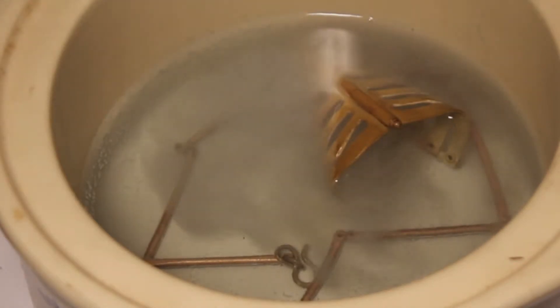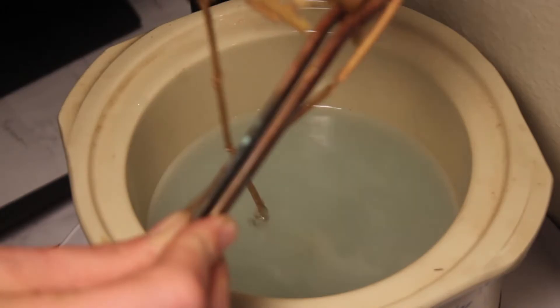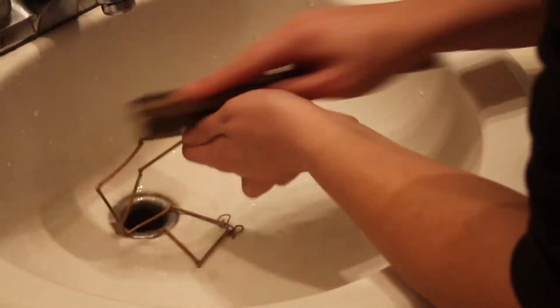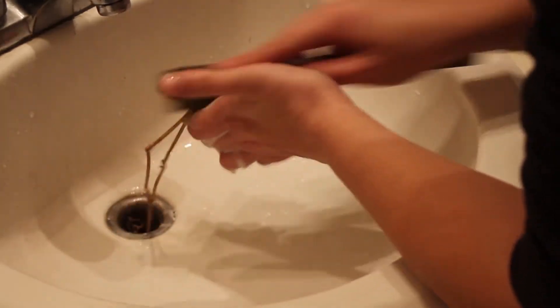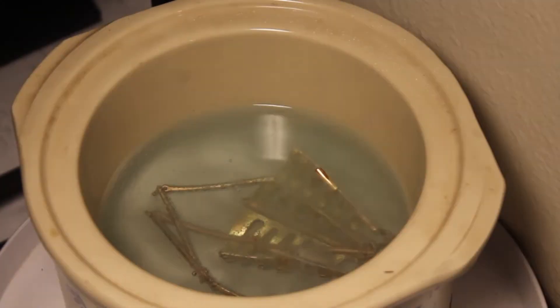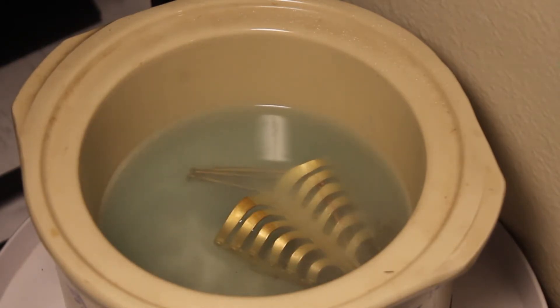It is important to flip the piece as the hydrogen peroxide pulls from the top. Once you have a coating that's taken off, brass brush and return the piece back into the pickle. You'll notice again that a chemical reaction happens. Again, flip it over because everything is happening from the top. Once you've gone through several rounds of dipping and brass brushing...